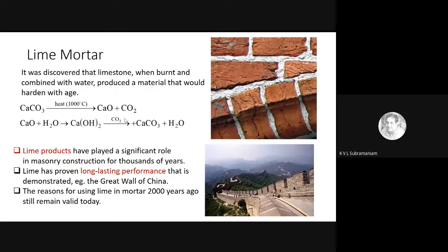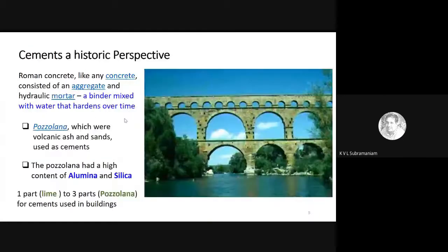Now, the reason I talk about this history is, if you look at the thread that is coming through here, is that people were predominantly using calcium-based materials. So if I just go to the previous slide, if you look at the pozzolana that the Romans were using, now we are finding that it had some calcium, but more importantly, it had silica and alumina in it. And the silica is something that we'll see later plays a very important role. And they, of course, mixed it with lime. So lime is the calcium source.